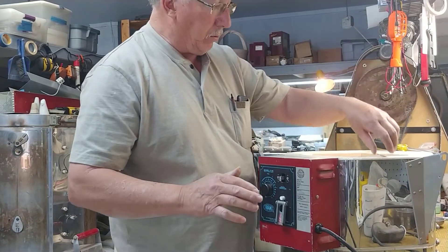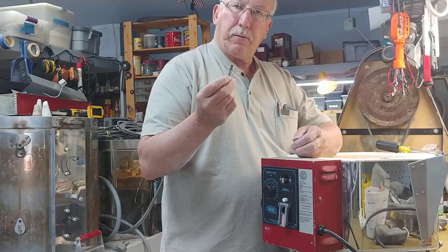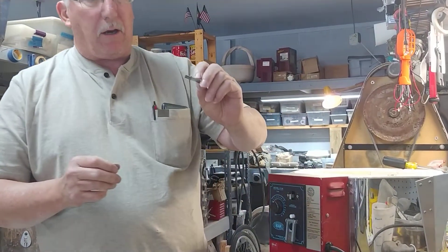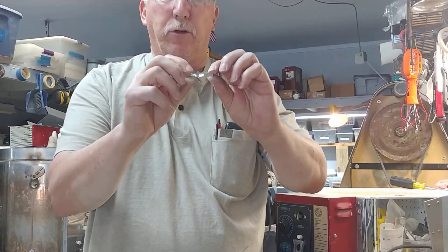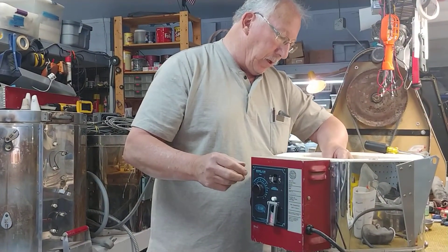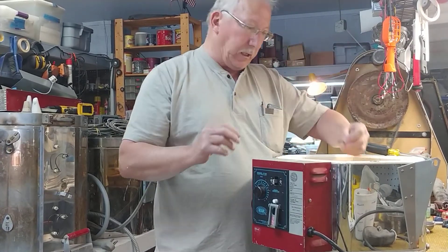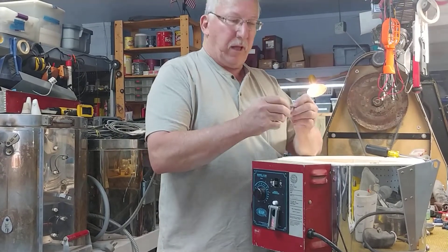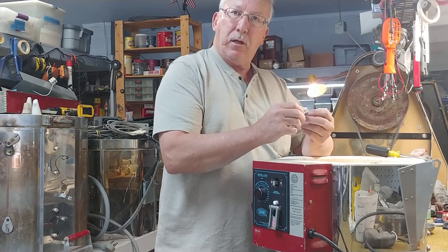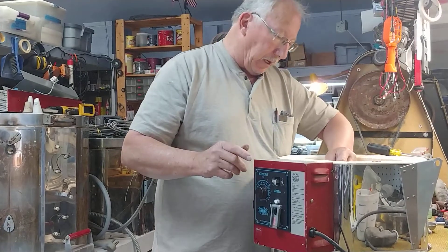Take your guide key out. Another thing you want to do is look at your cone supports. Cone supports have a long shaft and a short shaft — the long shaft is what goes inside the tube. This customer was actually firing with the cone supports in the opposite direction, so the long end was sticking into the chamber more, which would change the melting or alignment of the cone. To give more stability, the long part goes inside of the tube.